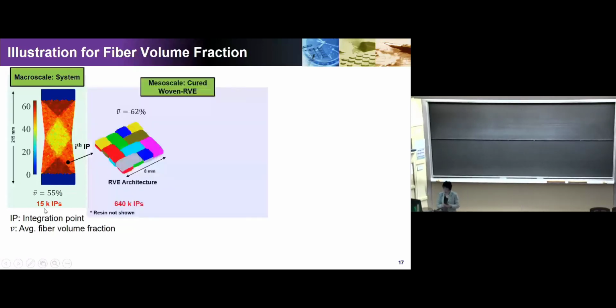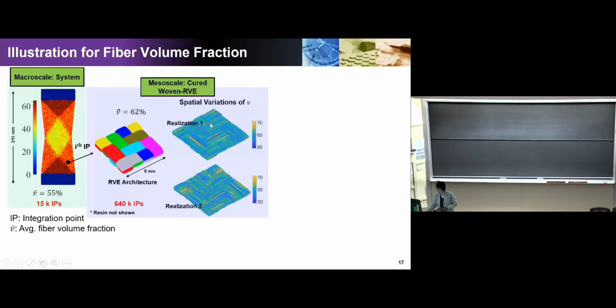If you amplify one integration point, now it becomes an RVE at the mesoscale level. And this woven composite has 4x4 tows, we call each of them a tow, right? And then 4x4 together. Even if you do multiple realizations, for this particular point the average volume fraction is 62%, and this color shows the variation of the volume fraction. And they can be quite different. This is just one realization of uncertainty or variation. This is another realization, and you can see that the volume fraction varies from one location to another. It could be anywhere from 50% to 70%.